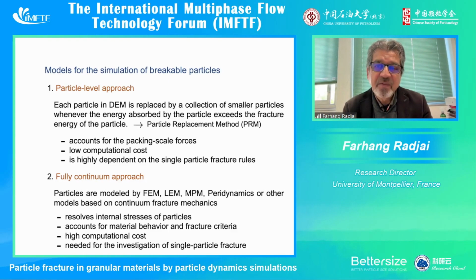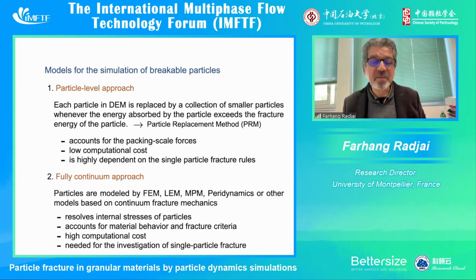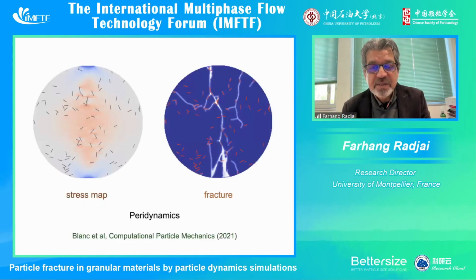Then we have the fully continuum approaches. So we can, of course, implement peridynamics, material point method, finite element method, fracture mechanics, so discontinuities inside continuum mechanics. And here the advantage, of course, is that we can resolve internal stresses of the particles. So we can account for material behavior, but it has a very high computational cost. Here you see an example.